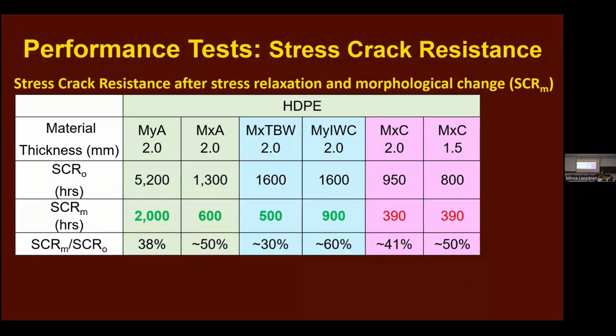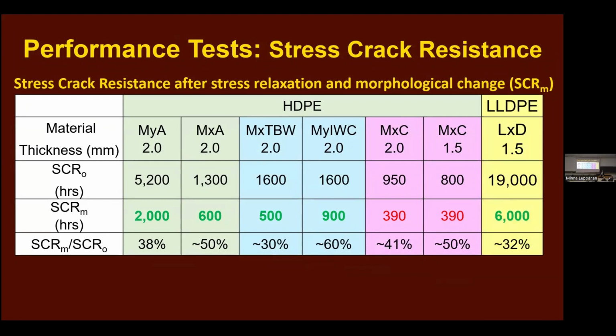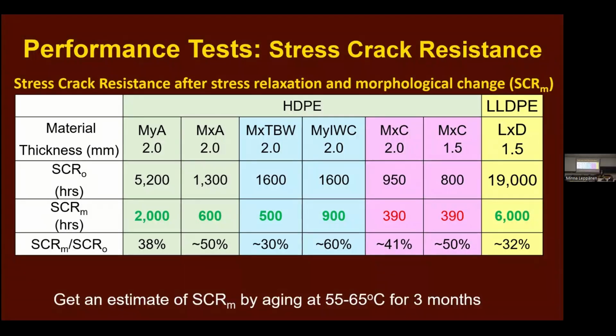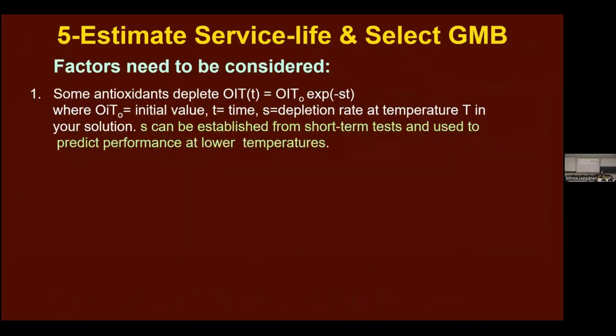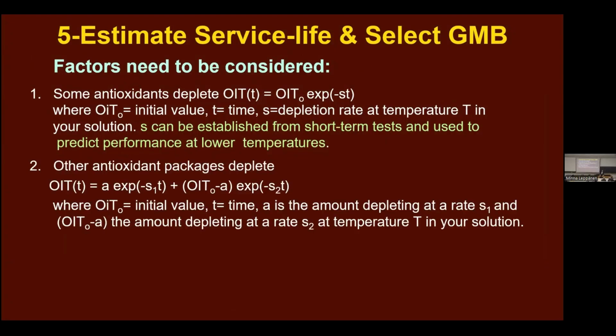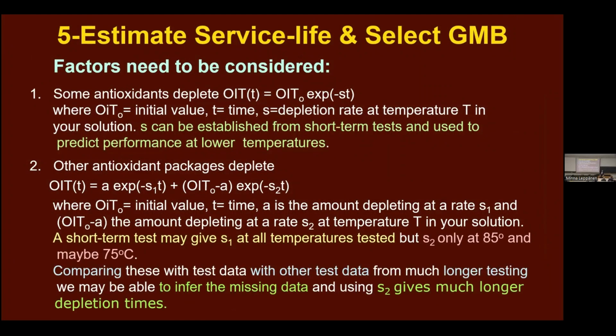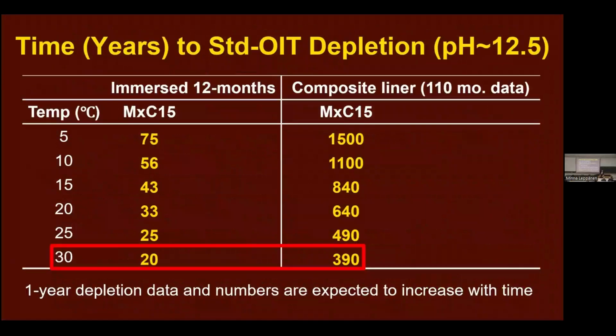MYA here has got the best resin. And then there's LLDPE. And it has 19,000 hours to start with, but 13,000 of those aren't real. 6,000 are. So we get that by aging at 55 to 65 for about 3 months, and we get that change. We also monitor the antioxidants, and we can use the data to predict performance into the future. I won't go into how we do it. Have to accept for the moment that we can.